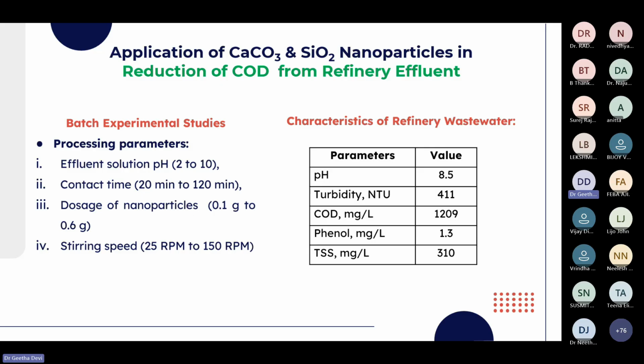We collected the refinery wastewater from Petroleum Development Oman, a leading oil company in Oman. These are the characteristics of the refinery wastewater which we collected from PDO. Here the processing conditions were varied: pH from 2 to 10, contact time from 20 to 120 minutes, dosage of nanoparticle from 0.1 to 0.6, and stirring speed from 25 to 150.